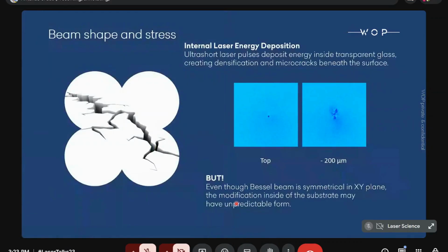Okay, so as I mentioned, a very important thing is beam shape, which is related to the stress which is induced in the glass volume. If we place Bessel beam pulse focus on glass, at the top we can see a very nice, very round spot, which looks very smooth. But if we go a little bit deeper, in this case 200 micron under the top surface, you can see that it is quite irregular, and often it has quite unpredictable form.